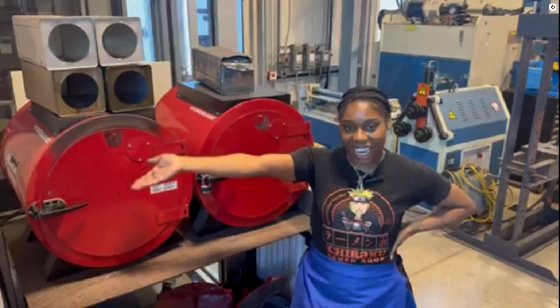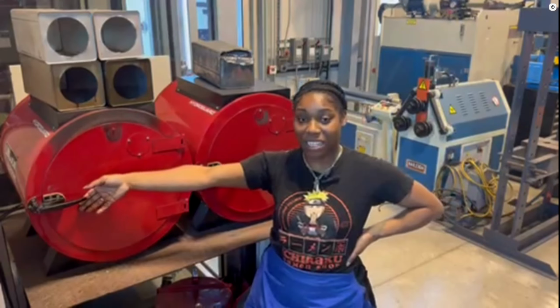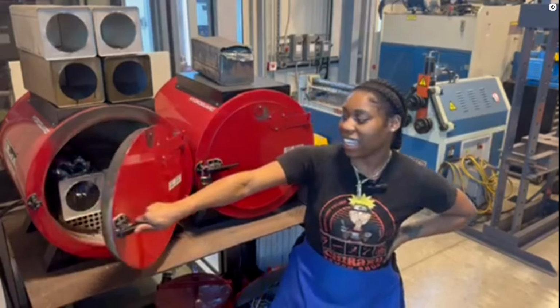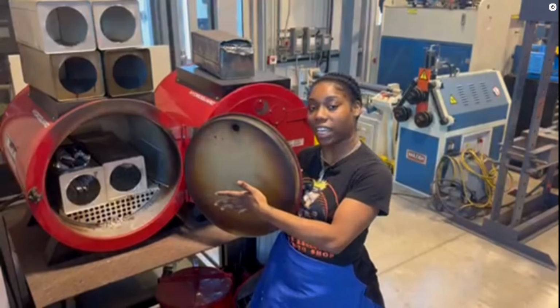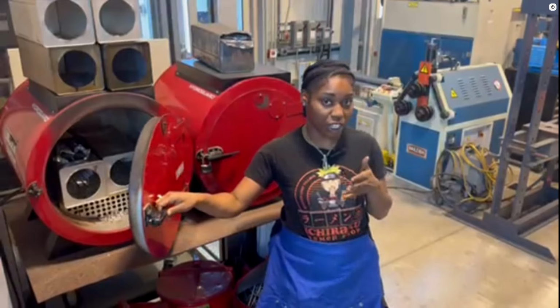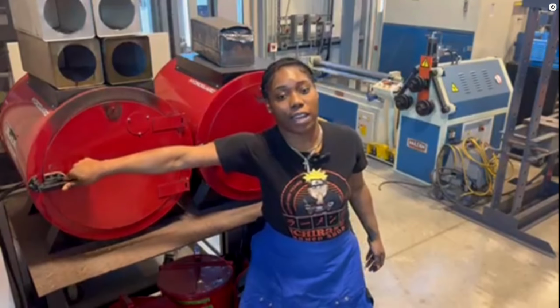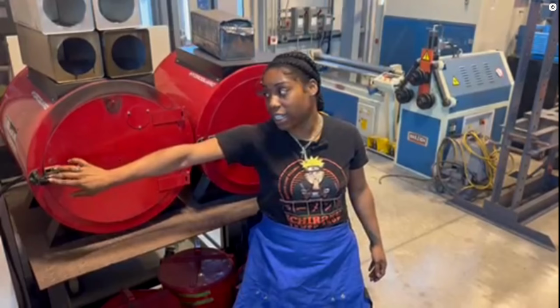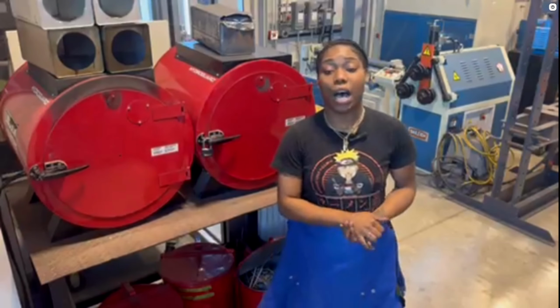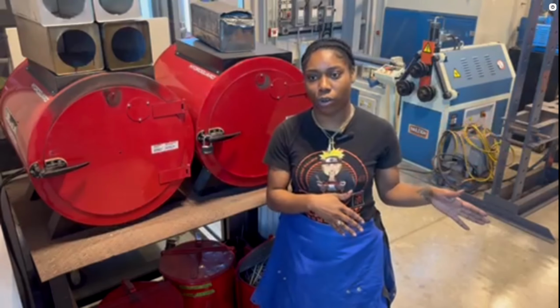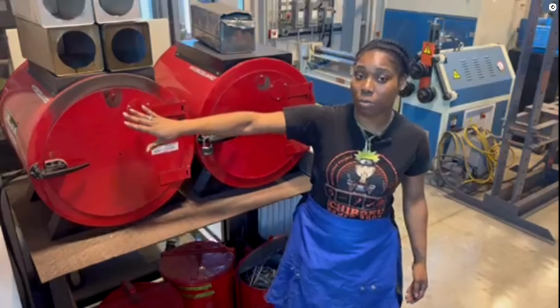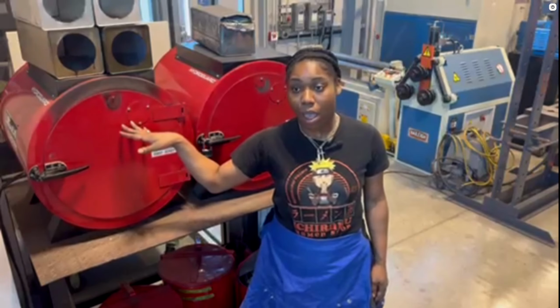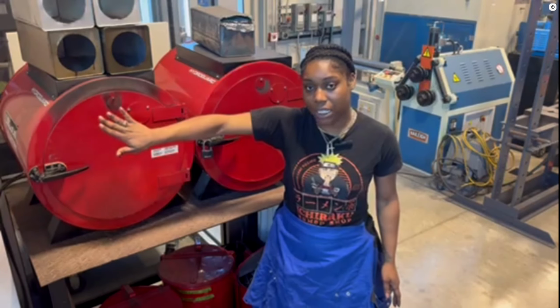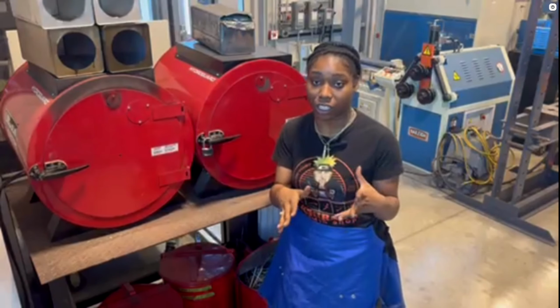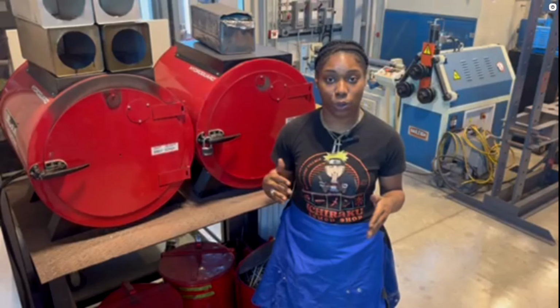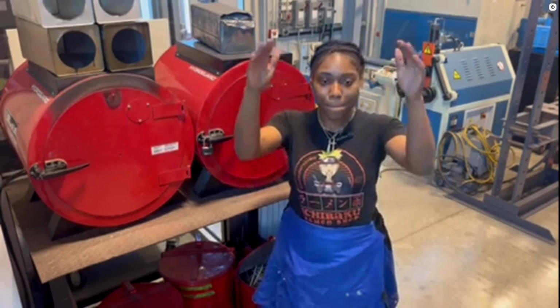Hey guys, in today's kitchen, we're gonna go ahead and talk about some low hydrogen electrodes. Today I have some 7018 rods sitting in the oven because they are moisture sensitive. I do want to keep them in the oven at about 250 to 300 degrees since I opened them. If they're not open, I keep them in the room. Now, if they do get exposed to moisture, I can rebake them, but it has to be between 500 to 800 degrees depending on the manufacturer's specs, and only for about 1 to 2 hours, no more than that.